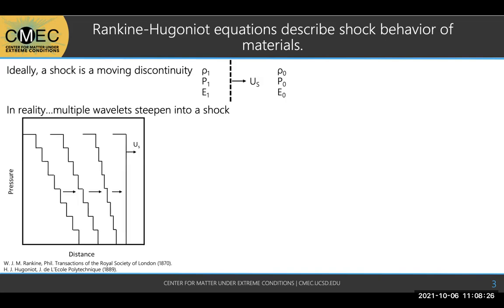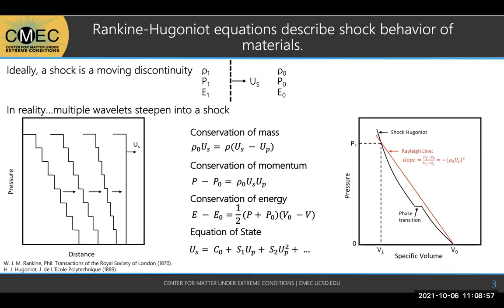Next. So in reality, you actually have this sequence of small jumps. You've got the very first velocity jump, and then the subsequent one is going to be traveling faster because the previous one increased the sound speed. So essentially you've got this steepening of a bunch of these little wavelets that end up forming the main shock wave. Next.